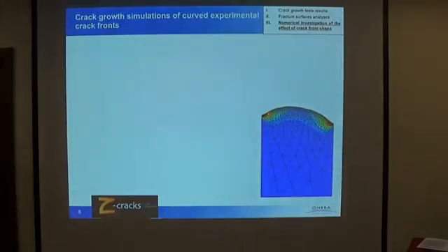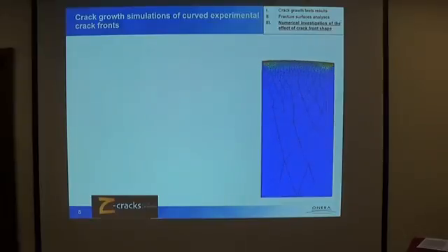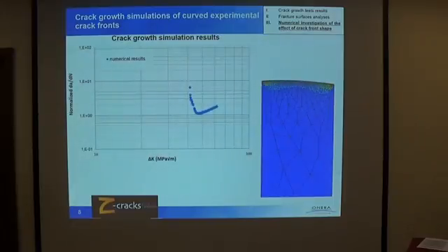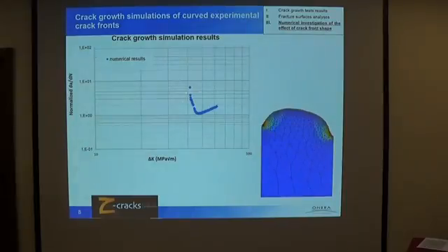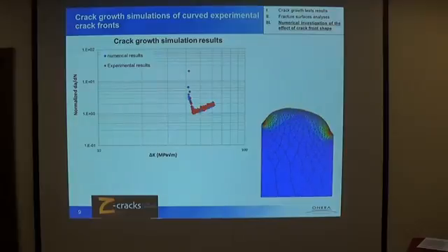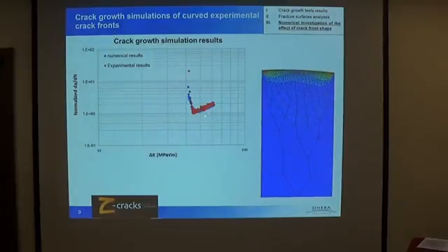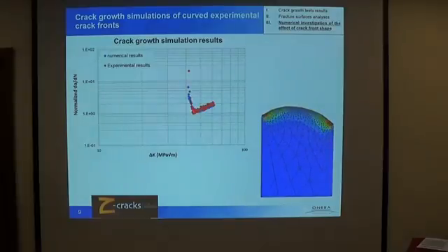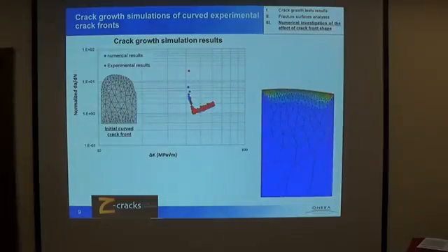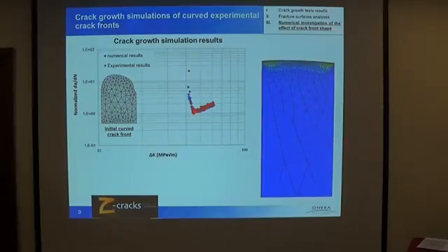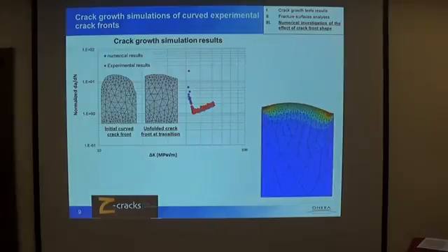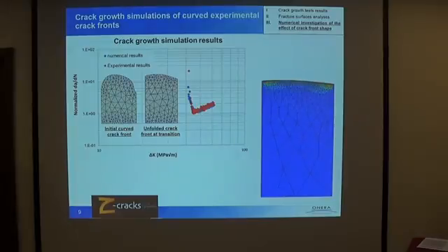So you can see that if we make a curved crack propagate, at the beginning of the propagation the curvature will quickly unfold, and afterwards the crack front is almost straight and propagates mostly by translation. By applying the DCPD method, in order to get the da/dN and delta K curve, we get, once again, this kind of junction, and it is found to be in very good agreement with the corresponding experiment. From this, we are able to say that this tangent corresponds to a geometrical effect on the DCPD method, since at the beginning we have a curved crack front, and at the shoulder of the tangent we have an almost straight through-thickness crack. So this is believed to be the sign of an unfolding crack. There is an effect of crack curvature on the DCPD method and the crack growth rate measurements.